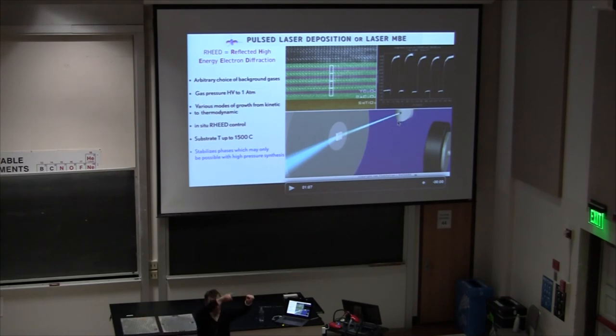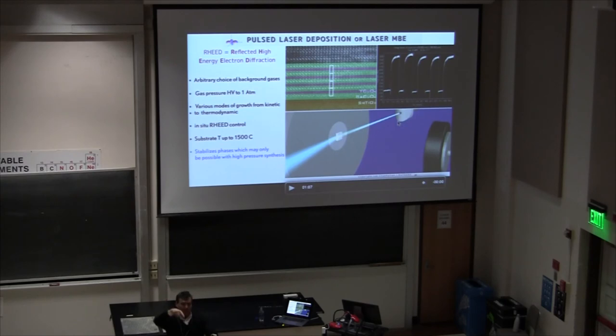Continue to 60%, 70%, 80% coverage and the intensity comes back up — 100% covered with the new layer, and boom, it returns to the original intensity: one wiggle, one monolayer. So I open my shutter, do the pulses, watch the wiggle go down — one monolayer. Want more? Boom, two. Three? Boom, three monolayers — stop. That's it. The time scale for growth of one unit cell is your question.